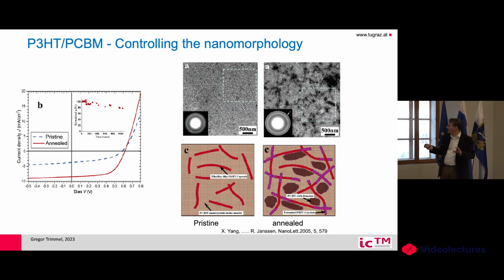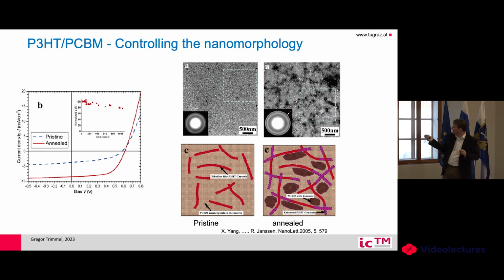And actually what they did, they made a thermal annealing step at 150 degrees. So the polymers start to agglomerate, they start to crystallize. And after this step, only 10 minutes, you see black. I think you can see this different morphology. Yeah? So you see black spots, you also see larger fibrils.